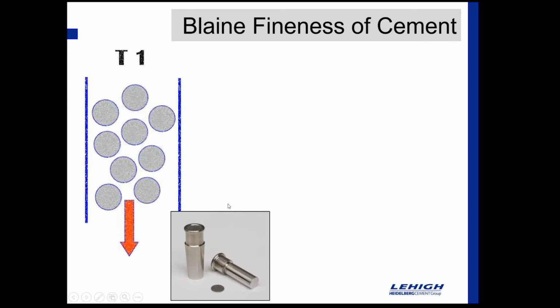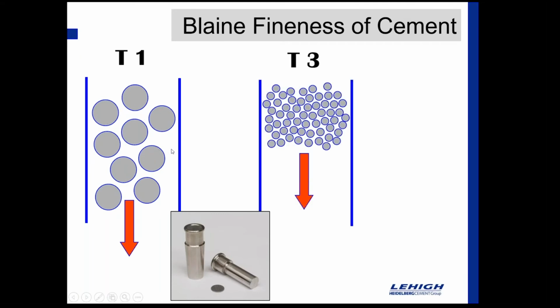And so here's how I kind of look at that. If I've got type 1 cement that I'm placing into that cylindrical test measure, then that's about maybe how big those particles are. If I was going to put type 3 in there, they're much smaller and they're much more tightly packed together. And so what happens is the air pulls through quicker in a type 1 than it does in a type 3. So a type 1 has a lower Blaine measure than type 3 does.